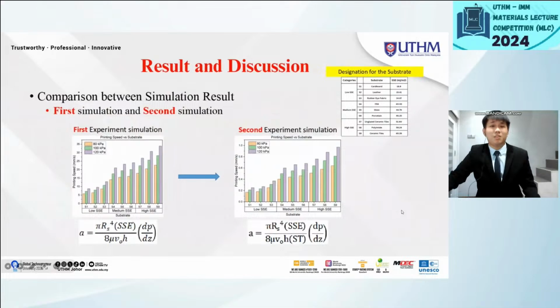Next, I would like to discuss the comparison between the first simulations and the second simulations. The graph clearly shows that integrating both the substrate surface energy and ink surface tension variables into the existing models results in a decrease in printing speed. In the second simulations, printing speed ranged between 0.17 and 0.97 mm per second. This decrease in printing speed after incorporating the surface tension variables brings the result closer to those observed in the preliminary simulations.